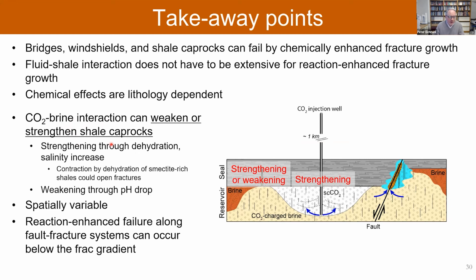Very carbonate-rich caprocks may not be good either. Something that we did not observe, we don't have very smectite-rich shales in our samples, but while we see a strengthening because of dehydration, a very swelling clay, smectite-rich clay may actually contract and open fractures because of dehydration. So there's two effects that need to be accounted for.